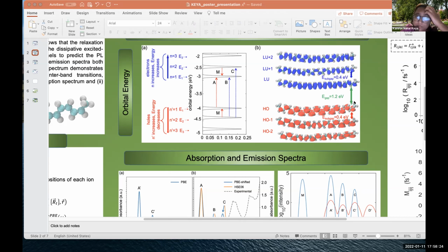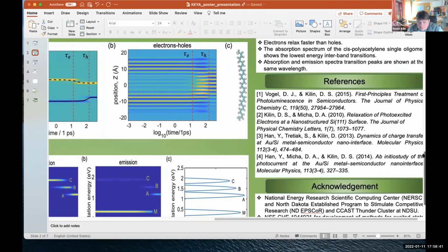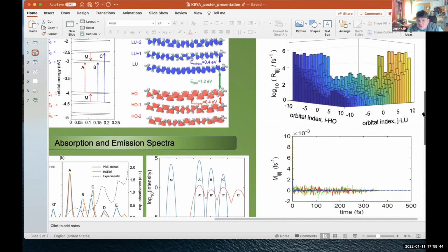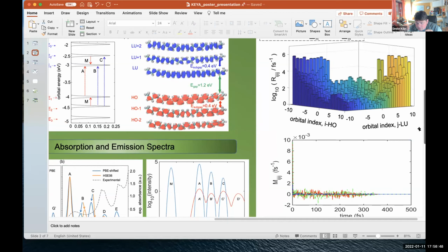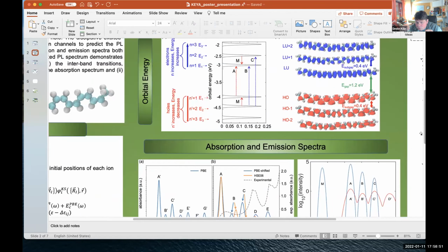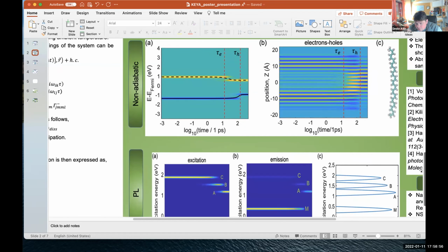Right? Okay. And the mechanism of how this release of energy happens is the figure that K is not showing right now, but what is on the right panel. Yes, the non-adiabatic couplings. So since atoms are moving, the motion of atoms launches electronic couplings and leads to transitions between levels.